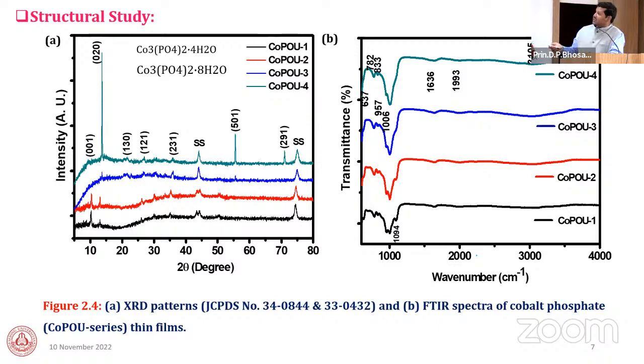Similarly, in the FTIR study, peaks below 900 are the metal oxygen peaks, and peaks between 900 and 1000 are the phosphate PO bonding, and the peaks above 1000 are the different kinds of water molecules. And also the interesting thing is that with increasing urea concentration, the hydrous content is also increased, and you can see in this shape that the hydrous content increases with increasing urea concentration.